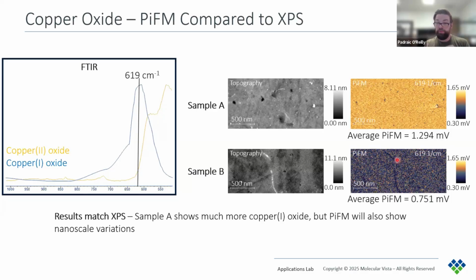However, as I mentioned earlier, due to the sub 5 nanometer resolution of PiFM, it can be used to measure individual pads all over a wafer, but also any variation within those pads themselves.